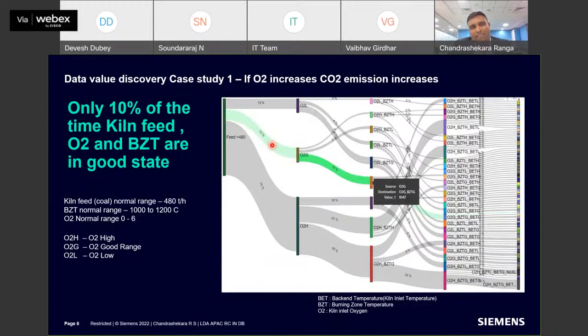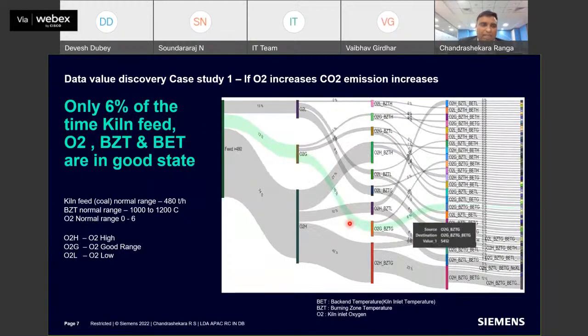When we drill down further, we notice that only 10% of the time kiln feed, oxygen, and burning zone temperature are all in the desired range, and in all other cases it is either high or on the lower side. Further analysis also showed that only 6% of the time the four parameters are in good condition: kiln feed, oxygen, burning zone temperature, BET, and all of them.